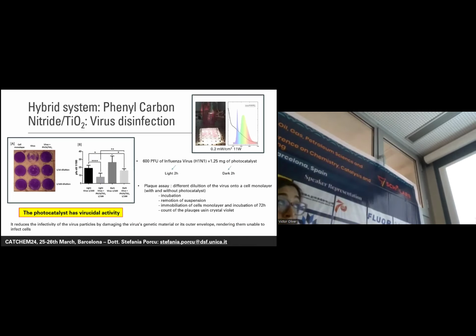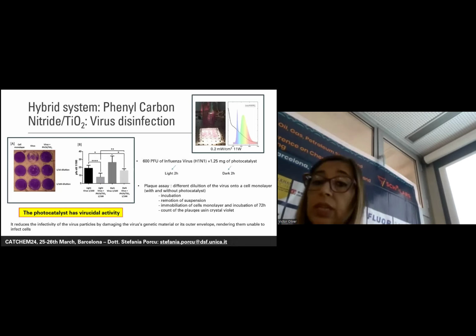The second application we studied for this material was virus disinfection, always using photocatalysis as the major technology. So what we did was to try to apply it for the disinfection of H1N1 flu virus by mixing 600 PFU, that are the units of virus, with a precise amount of our photocatalyst, and we did multiple tests. One with the interaction with the light of this system, and one control test was just kept in the dark for being sure that the results came from the photocatalytic process.